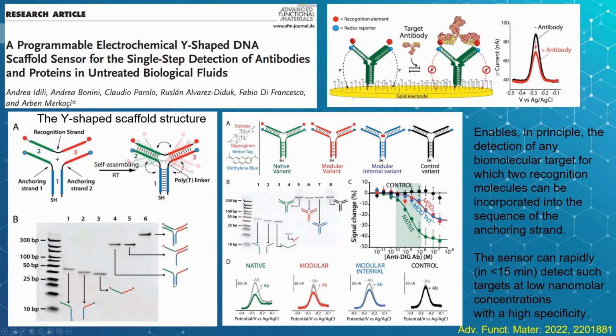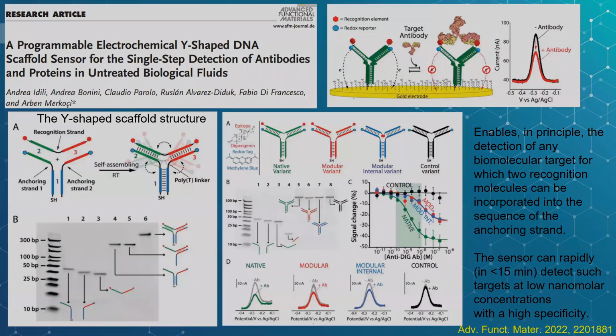So by using this antibody, in this case as an analyte, we were able to detect very sensitive changes of the current. Of course, these were controlled and also compared with different structures using different variants of the DNA structures, giving different responses that you can modulate according to the analyte you want to detect. The sensor was very sensitive and very fast: in less than 15 minutes, detecting down to nanomolar concentrations, with very high specificity.